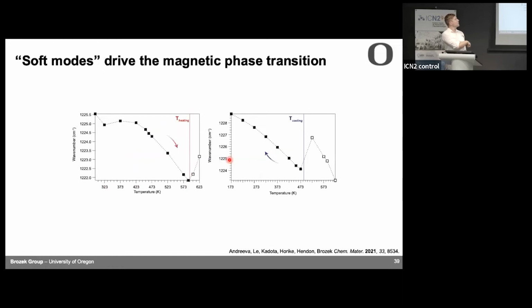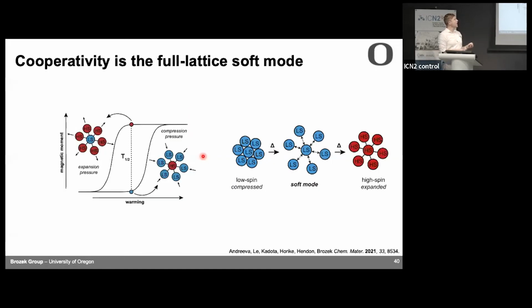So that was nice. But we saw something else, that not only does it redshift, but right at the spin crossover temperature, it inverts and starts to blueshift again, kind of like I was showing you for strontium titanate. In fact, this is exactly the hallmark signature of a soft mode: you should see it redshift up until the phase change temperature, and then it regains its energy. And so this is telling us that the triazolates are really acting as the soft mode that causes the spin crossover. And so a way of thinking about this is that when you go from a low spin system, the bonds are much tighter, they're much stronger.